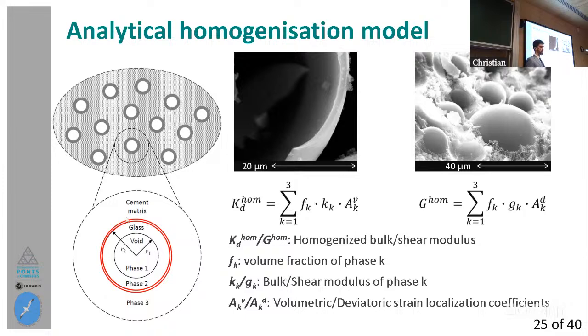Then we have phase 2, which is the glass of the outer shell of the sphere, which can also be seen there, this outer part. And then we have the cement matrix, which can be roughly seen in this image here, surrounding all the spheres. There are presented the main equations of the model, in which we see that the homogenized elastic parameters depend on the volume fraction of each phase, the elastic parameters of each phase, and also this Av and Ad, which are volumetric and deviatoric strain localization coefficients, in which we have worked quite a lot.